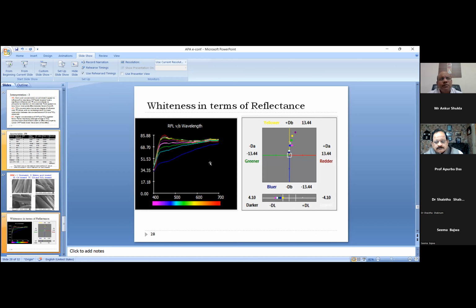Whiteness, in fact, there was some reduction in whiteness because of the citric acid treatment. As such, citric acid doesn't cause much yellowing. The yellowing takes place only when the curing temperature is very high. If it is about 170 degrees centigrade or so, that time you find a lot of yellowing, and we also experienced it. But that is why we restricted it to 150 degrees centigrade only, and there was not much yellowing. And barring a few cases here, you find that they're almost concordant graphs. So the whiteness was by and large retained.